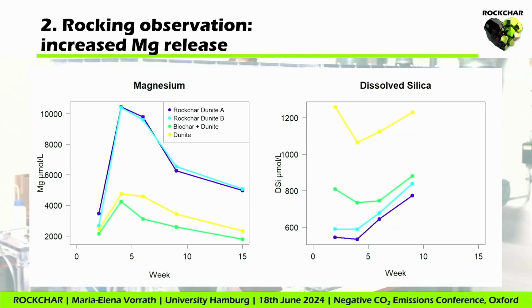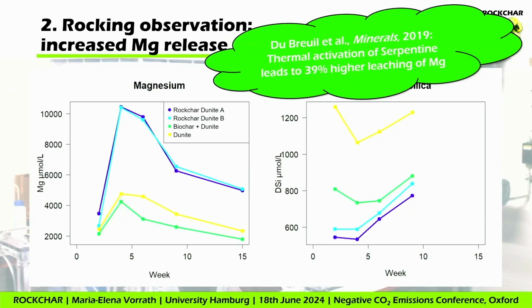I hope that's clear. So something is weird here, and I had a chat about it with Ingrid, who will also talk in a few moments, and she mentioned serpentine. So the dunite I used contains 11% serpentine. And if you heat serpentine to 600 or 700 degrees, you thermally activate it and it becomes more reactive. My ROCKCHAR was at 650 degrees, so I have obviously activated it, and now the dunite in my ROCKCHAR is more reactive than the simple dunite, which was not heated. This is a possible interpretation. This is not the end of the story, but this is what I can see so far.